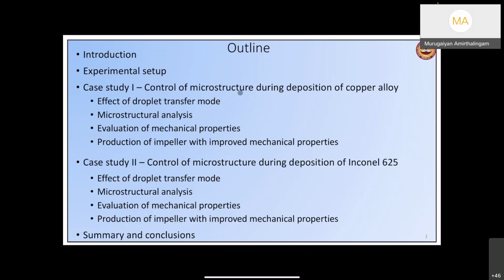One example I'm going to show here is how we can manipulate the process parameters in such a way that we can get an equiaxed microstructure. The microstructure we get out of forging, for example, or hot rolling or cold roll annealed cases, is an equiaxed microstructure. So if we want to use additive manufacturing to produce a component that is going to replace the conventionally manufactured component, then the mechanical properties should meet the in-service demand, isn't it? Otherwise, it may not really be advisable.